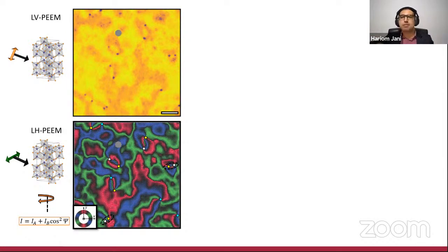So in some sense, as the Morin transition has occurred, what has happened is that the out-of-plane region has sort of shrunk and gotten trapped. And because it cannot unwind, it remains as a sort of metastable topological object, persisting until higher temperatures.